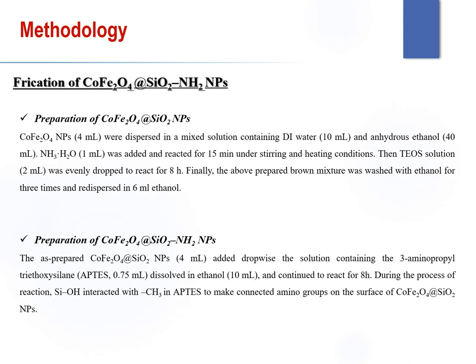The synthesized CoFe2O4 nanoparticles were dispersed in a mixed solution containing DI water and ethanol. Then, ammonium hydroxide was added to react for 15 minutes under stirring and heating conditions. Then, the TEOS solution was added to react for 8 hours.